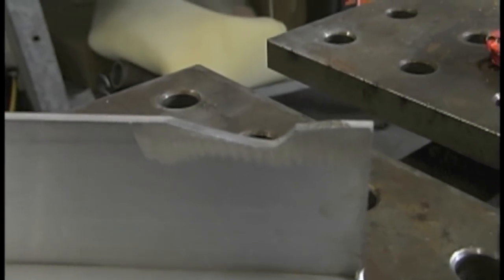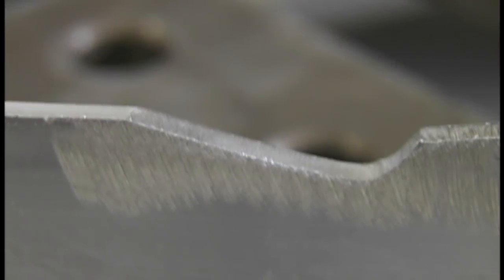This is 1/8 inch thick, 125 thousandths, roughly 3 millimeter or 3.2 millimeter. And again, I'm using the same size electrode, just a little bit more amperage, and I light up nice and easy, let the cleaning action do its work, make sure I get a nice shiny puddle before I get started, and then just progress with a dip and pause and dip and pause, just watching the leading edge of that puddle, using just enough pedal, just enough heat to let that wet in but not dig in.